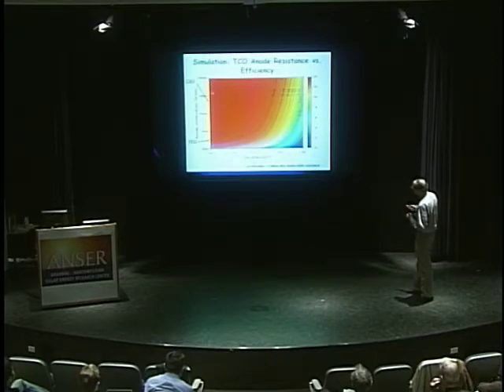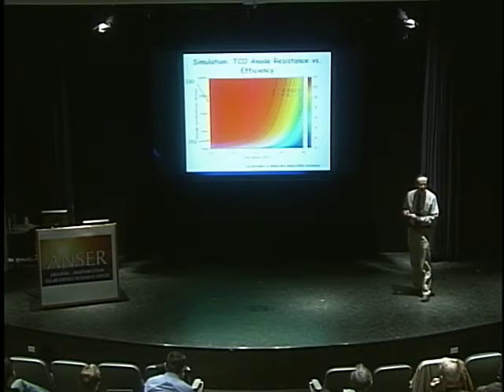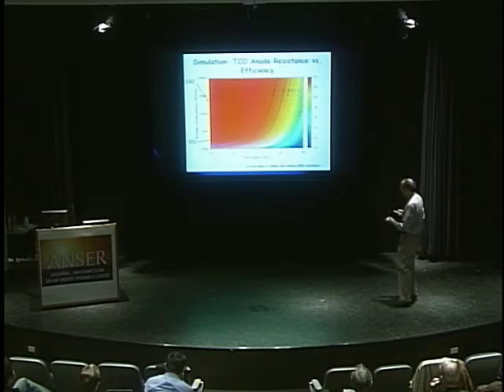To point out, I think the record TCO conductivities in the country are from Northwestern. There's one of Bob Chang's that has a slightly larger band gap, tin-doped cadmium oxide, and then CIO is one of ours, not CIA, but CIO, and we've measured as high as 17,000. So there are some really interesting possibilities for alternative TCOs.